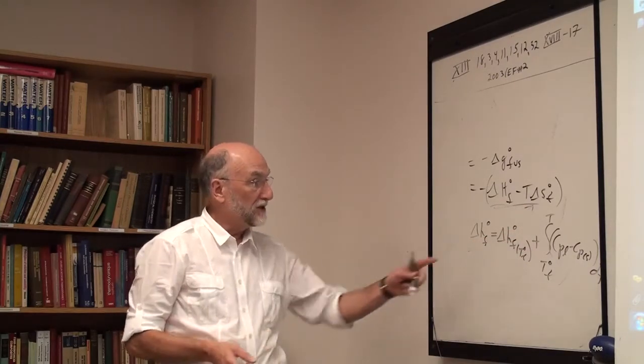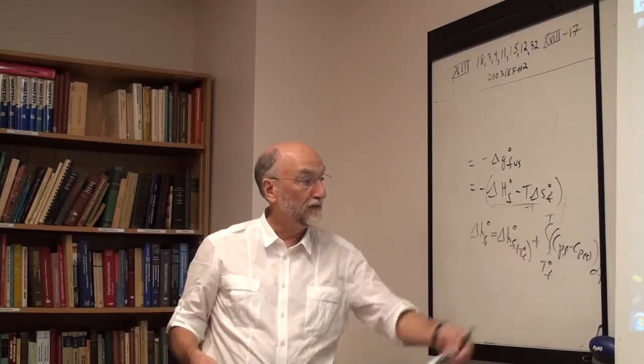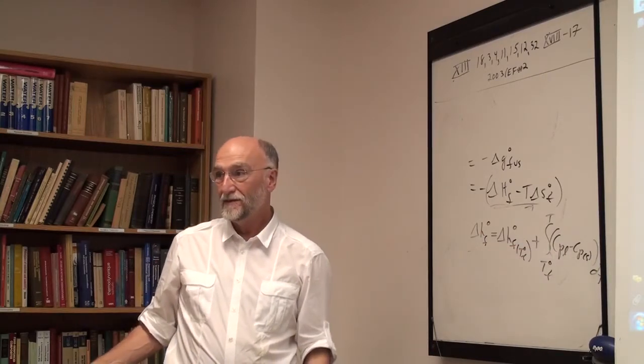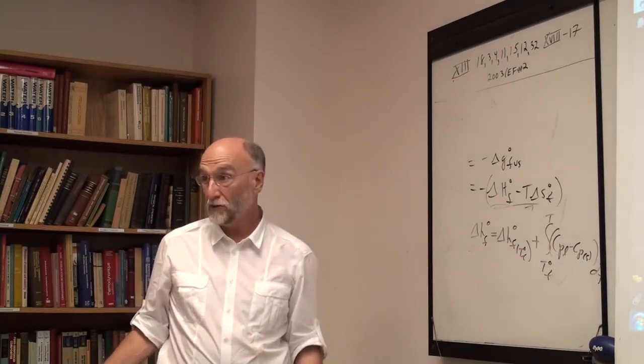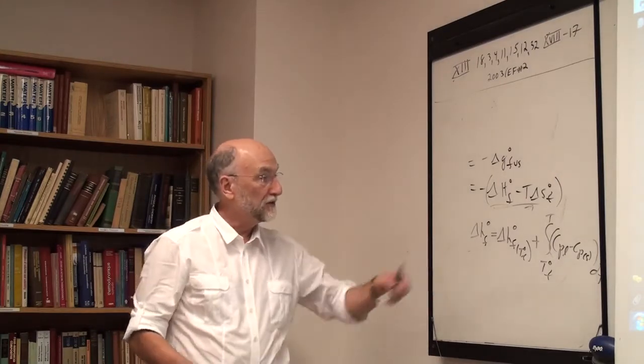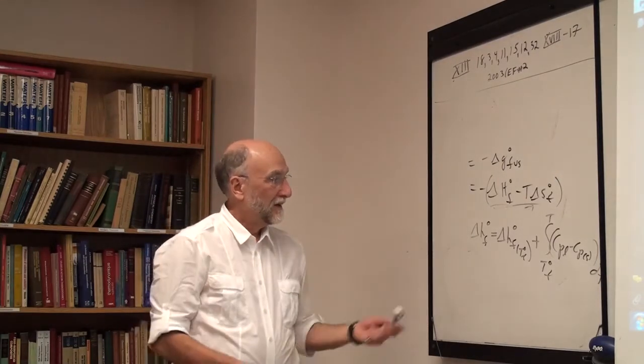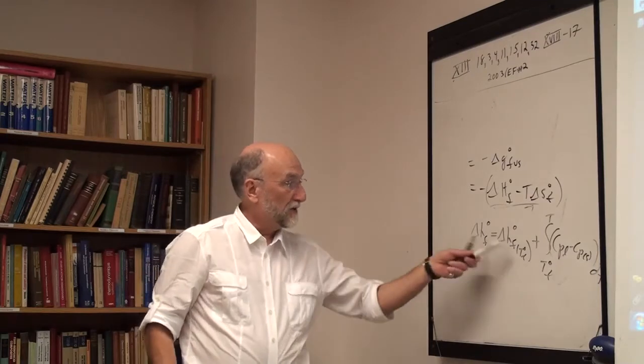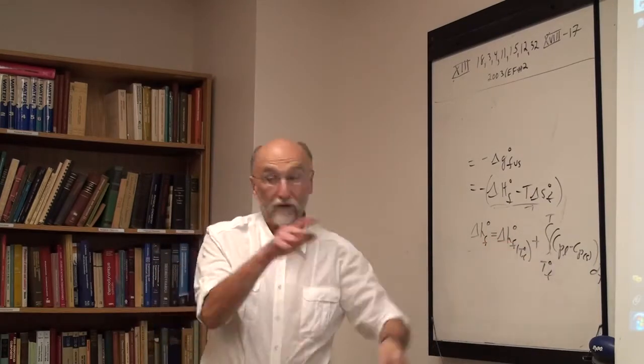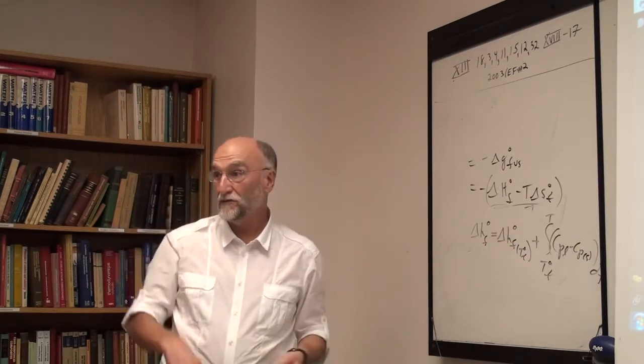Okay, so the heat of fusion is the heat of fusion at the melting point plus the integral of delta Cp dT. You agree with that? Okay, and the entropy of fusion is the entropy of fusion at the melting point plus the integral of delta Cp over T dT, and you get an expression for it.